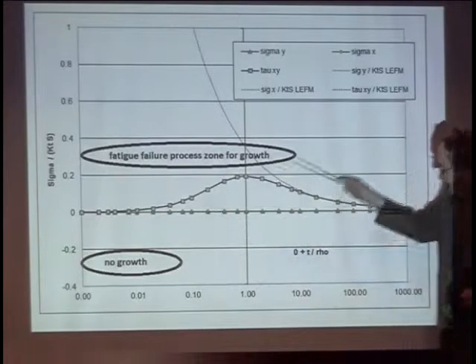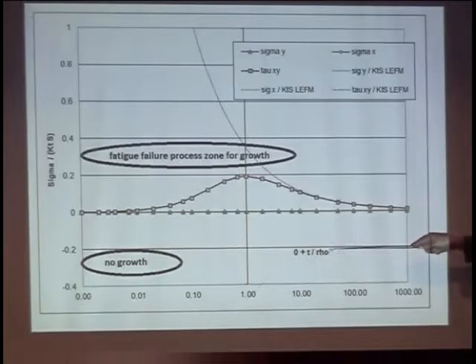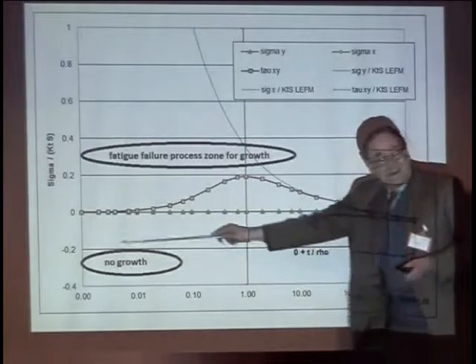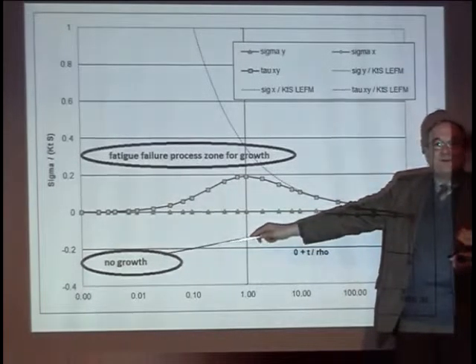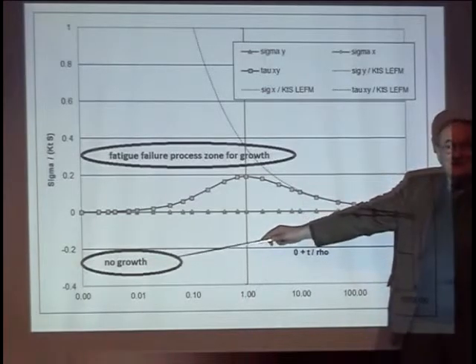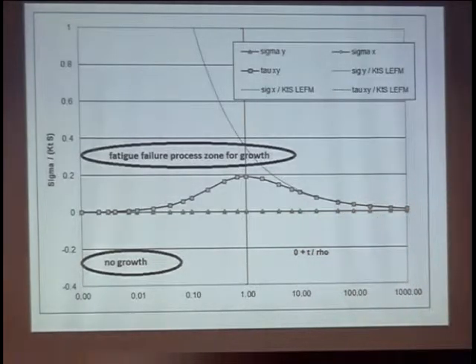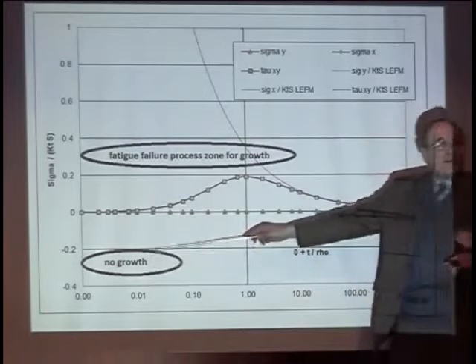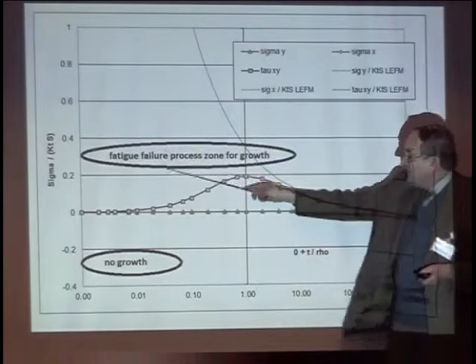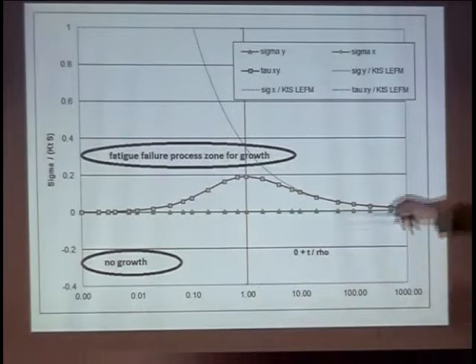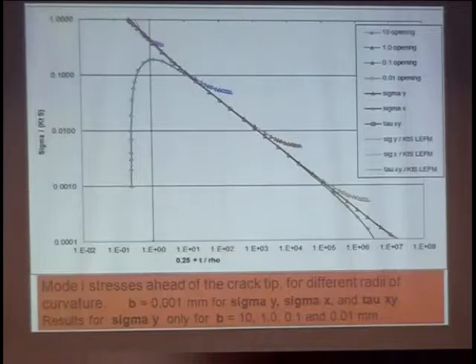The main difference between this and this is the value of rho. I said on my second slide that rho was 0.08 millimeters in the Sheffield tests, which makes our process zone on this normalised scale rather small, and too small to grow a crack. So I believe in blunt cracks. Other people do, I gather, from discussions up to now, but in this case the crack is too blunt to allow the crack to grow in mode 2. If we have a rather sharper crack, with still a finite radius of the crack tip, then we can actually develop a stress intensity and a decent driving force.